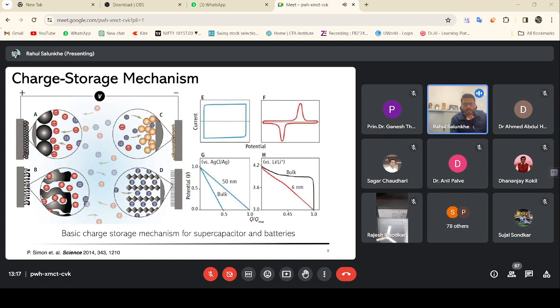Whereas in the case of pseudocapacitors, if we consider another type of capacitor, the ions can intercalate inside the material, and because of that they form certain redox reactions inside the material. They form certain electron exchange reactions, and because of that some redox reactions happen on the surface of the material, in a few layers of the material, and because of that some oxidation and reduction peaks can be observed as seen in this CV shape, figure F. Examples of these pseudocapacitors are certain metal oxides like manganese oxide or ruthenium oxide.